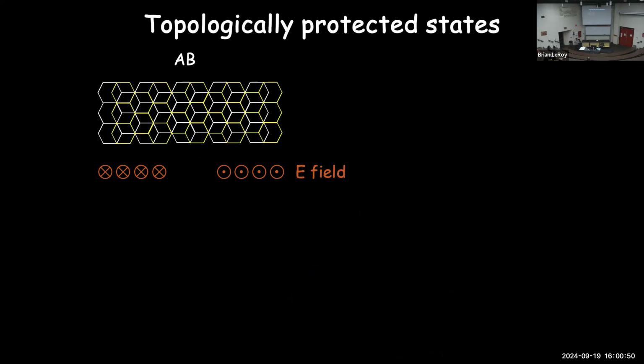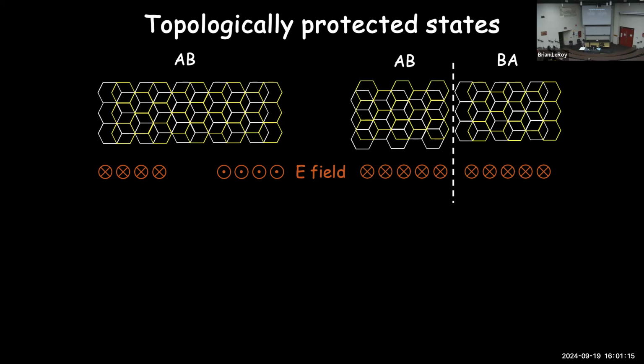And now let me show what that means in real space. If I have a uniformly stacked Bernal graphene, AB everywhere, and I have an electric field which I vary in direction from into the plane to out of the plane as I go across the space here, well, that's basically changing the field like this. At some point, the field is 0. And we have gapped regions on either side, 0 field in the middle. So it's conducting in the middle, gapped on either side. That is going to be exactly equivalent to changing the stacking configuration from AB, smoothly changing to BA, sliding the graphene on top of each other, but keeping a uniform electric field. So these 2 are equivalent to each other.